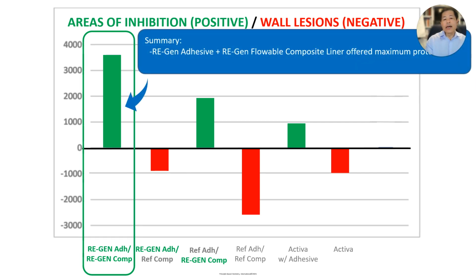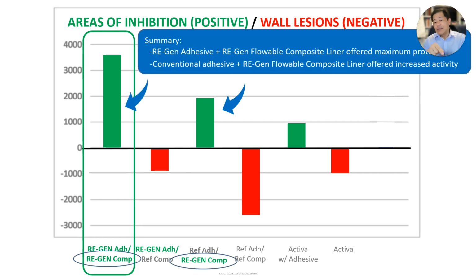The next one down had the Regen composite with the regular, traditional adhesive. So that was the second green bar. Now, the shortest red bar is when you had the Regen adhesive with the traditional composite. So what's happening here? Now, the composite with the Bioglass 45S5 is your reservoir of Bioglass. When you have the adhesive layer, which is very thin, we have some Bioglass there, but we don't have much. So we got a little bit of protection, but not as much as when we had a lot of that reservoir of Bioglass 45S5 in our composite.